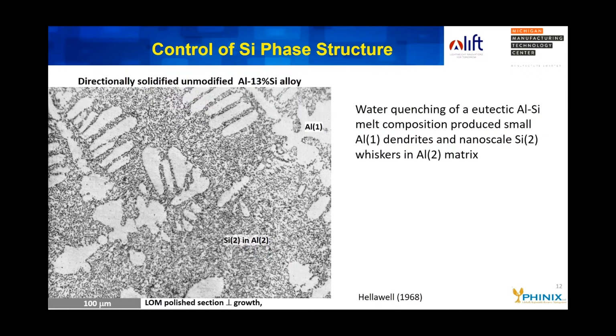And this is still a eutectic composition, but at very fast cooling rate, there are primary aluminum dendrites, and the silicon is then as nanoscale whiskers in the microstructure. And our objective in our work is to reproduce those silicon whiskers in the entire casting.